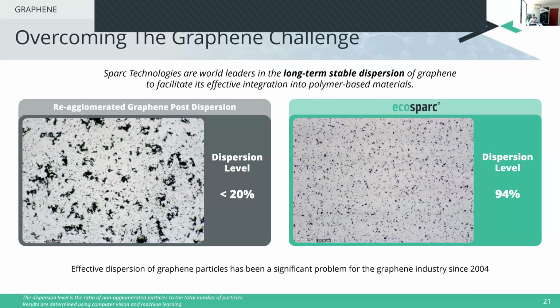The other key differentiator and challenge that we've overcome is being able to incorporate graphene into a usable additive. So a lot of the industry, in terms of the graphene industry, will provide graphene in the form of powder, and they'll recommend a certain dosage rate for a certain application, whether it's in cement or coatings or other industries that are being targeted. Now, that's a very difficult proposition for an end user because graphene, as I said, is difficult to handle. And when you put it in a liquid like a coating, it wants to re-agglomerate into larger particles. So when we approached the coatings industry a few years ago, a lot of the industry was saying graphene doesn't work. And one of the key reasons they were saying that is because of this agglomeration issue. We've definitely overcome that and developed stable additives that stay well dispersed, as you see on the right-hand side, and you need a good dispersion to have performance benefits in this particular industry.